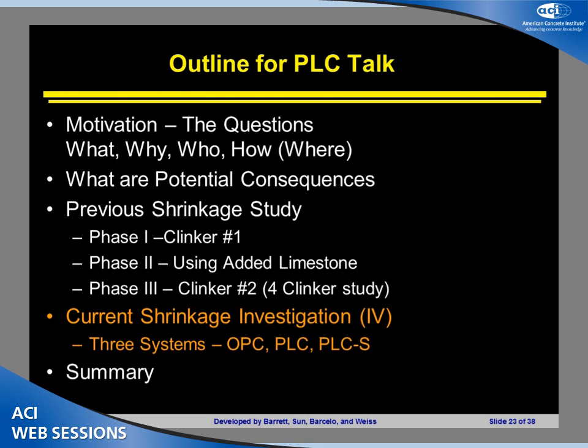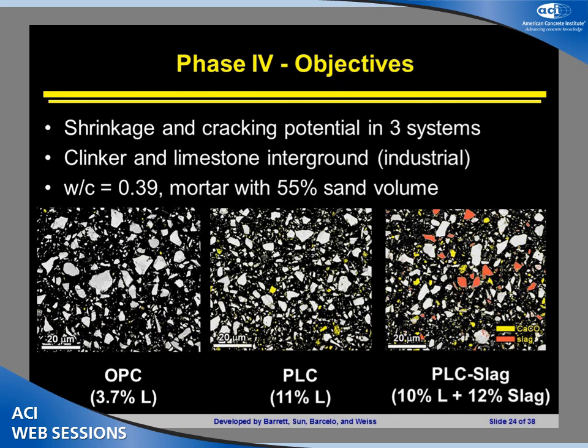So I really now want to get into a little bit more of the final study that we've looked at here, where we're going to get into a little more detail. We're going to look at the shrinkage and cracking potential in 3 systems. It's going to be the clinker with the limestone interground. And again, all the interground things that I'm discussing here are interground commercially, which has a lot different technology than if you're intergrinding these in a ball mill inside your lab. We're going to do a 0.39 and a 0.34 mixture, and for times I'm only going to show the 0.34 mixture with 55% by volume of sand.